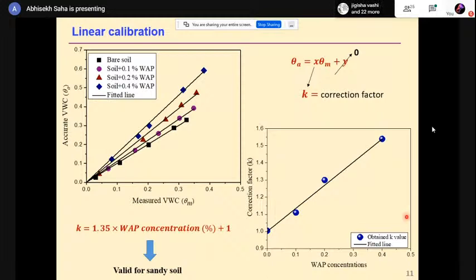And this correction factor is dependent on the water absorbing polymer concentration. With this equation, we can easily calculate the correction factor, which needs to be multiplied with the sensor measured value to obtain the actual result. And this equation is valid only for sandy soils.